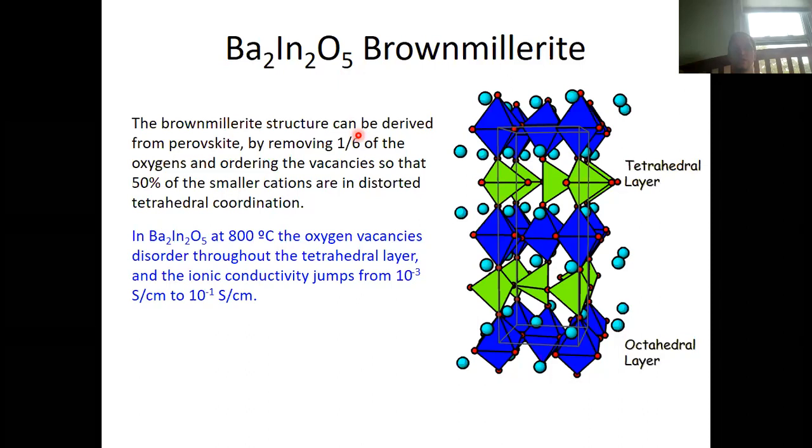So what is the exact structure? There must certainly be elements of the perovskite structure, and you see that actually here. So we have here layers of corner sharing indium O6 octahedra, and these are interconnected via near tetrahedral layers of indium O4 units. That reduced coordination number at indium within these green layers is because some oxygen ions are missing, so it's produced through the oxygen deficiency.